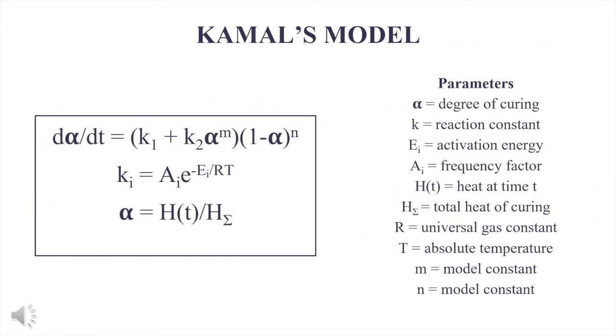The most accurate model for studying epoxy curing reactions is Kamal's model. This differential equation allowed us to determine the degree of curing, alpha, as a function of time. The reaction constants were calculated using the activation energy and frequency factor of the epoxy. The total heat associated with curing is also a known parameter, allowing us to calculate the heat released at any given time throughout the reaction. Kamal's model was developed through patterns in empirical data gathered by differential scanning calorimetry.